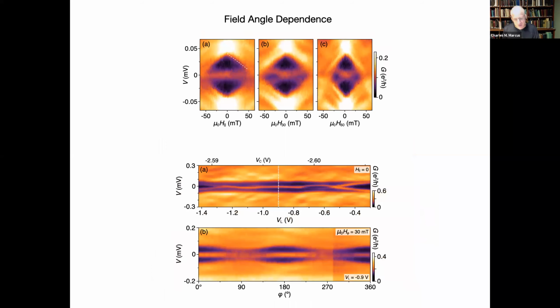Then we can play around and do all kinds of studies. We can swing the magnetic field out of the plane. If we go to, again, a place where it's about to split, we see that we apply the magnetic field along the axis. Very quickly, the density of states closes. Interestingly, the density of states of the parent superconductor does not have the same hysteresis as this critical current. Whatever it's inducing in the semiconductor is the same forward and backward. It doesn't have that effect.